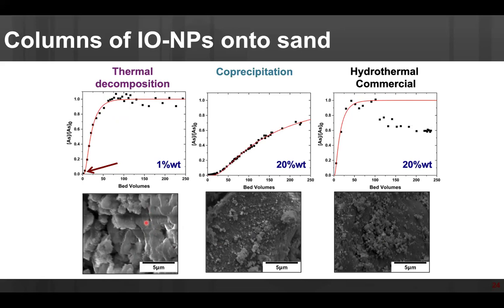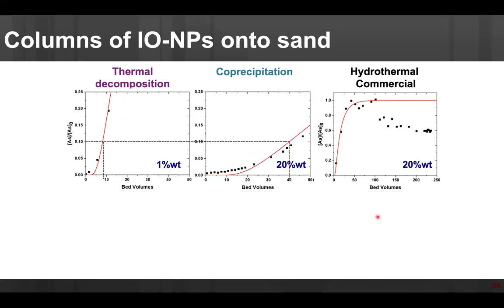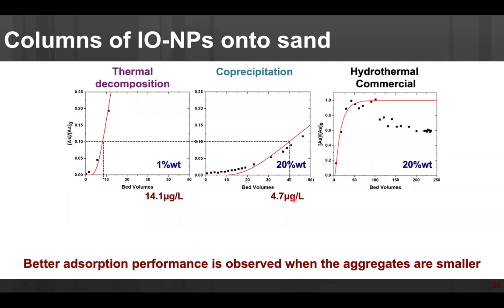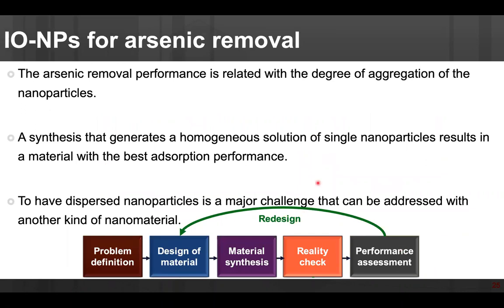So what we hypothesize is that you have a certain amount on the surface. In the co-precipitation, you can see the agglomerates of nanoparticles. These are bigger in the hydrothermal. If we quantify how much arsenic we are absorbing, even when the columns are not that good, we can find that the thermal decomposition, where we have nice nanoparticles deposited homogeneously, can absorb much more than the co-precipitation. So then, okay, we need to find a way to use the nanomaterial without generating a huge agglomeration, right? And that is the first redesign that I have to go back and do.